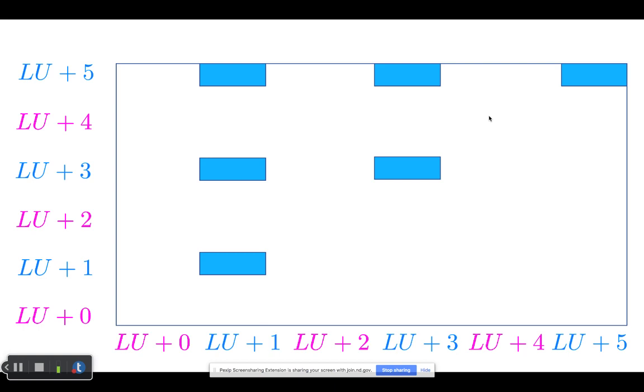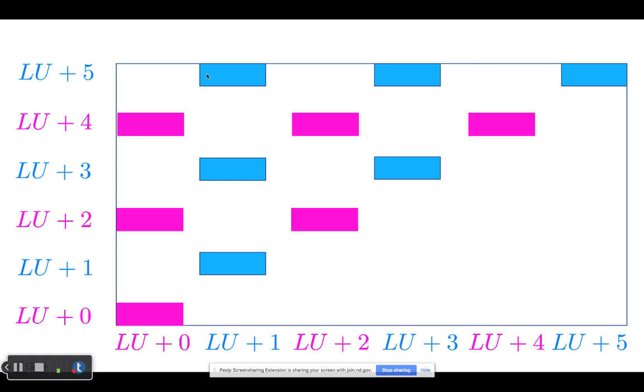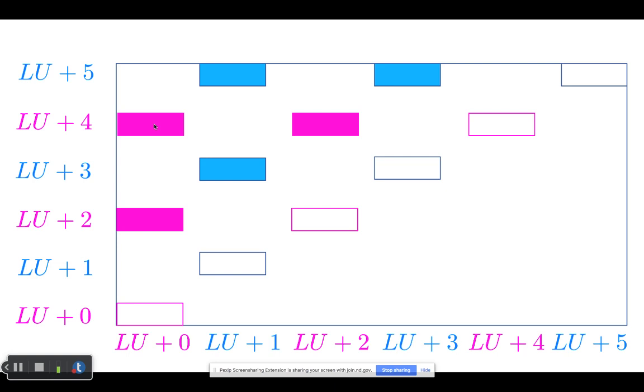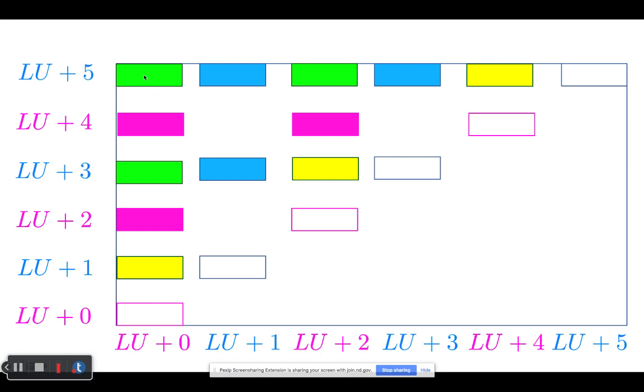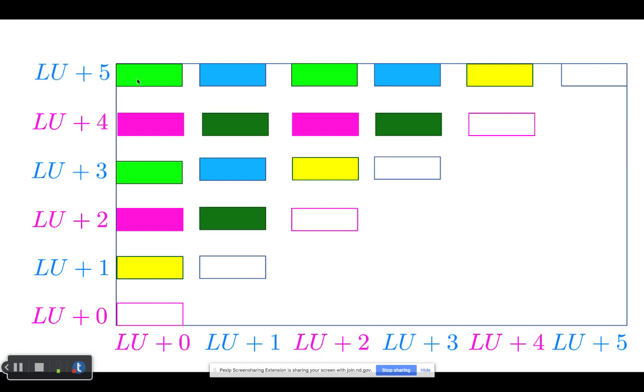15 transitions. So once again, first I made the final figure, but I understood that I cannot understand it. Therefore, I'm trying to introduce it in a slower fashion. So the transitions from alpha to beta, from cyan to pink, and transitions from beta to alpha, from pink to cyan. We also have to exclude diagonals, because it stays at the same place. In addition, we have light green for spin forbidden transitions originating from alpha, and dark green spin forbidden transitions originating from beta. In addition, plus 3 transitions between degenerate states.